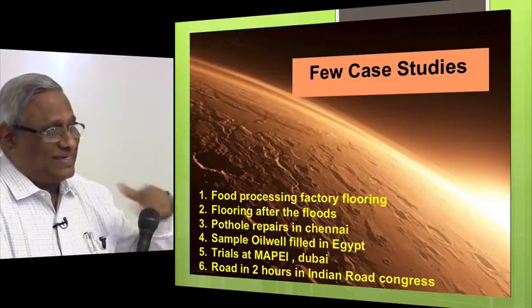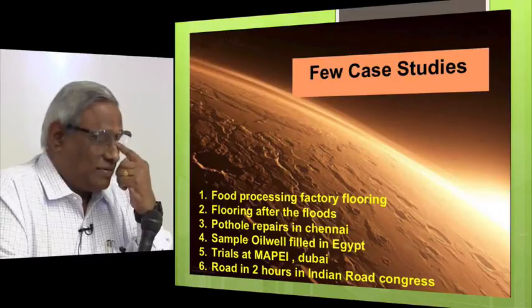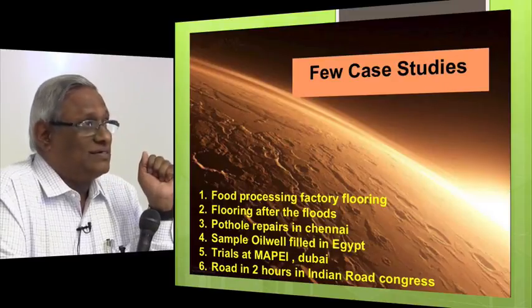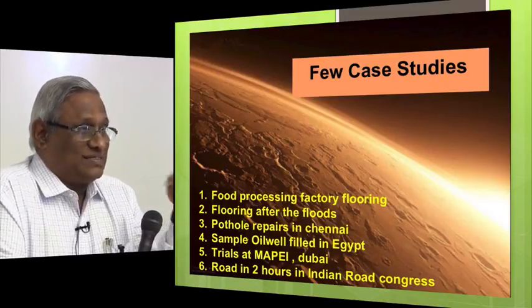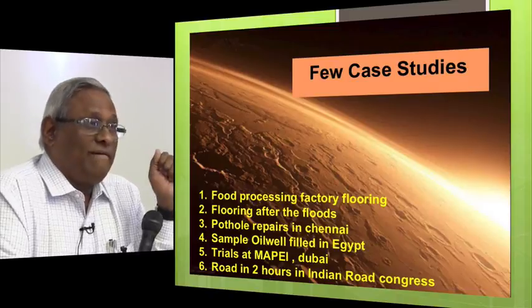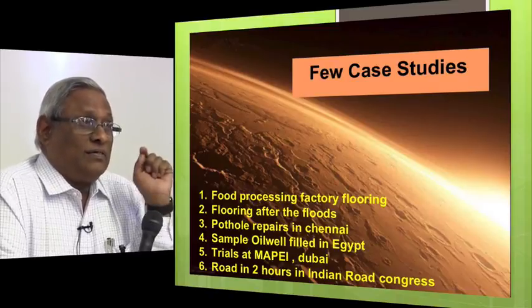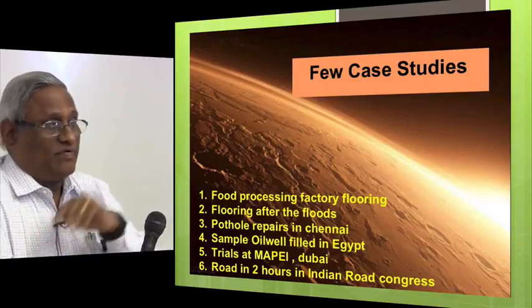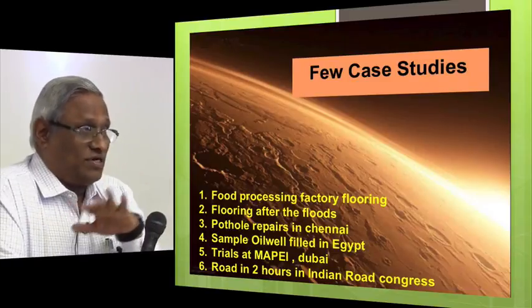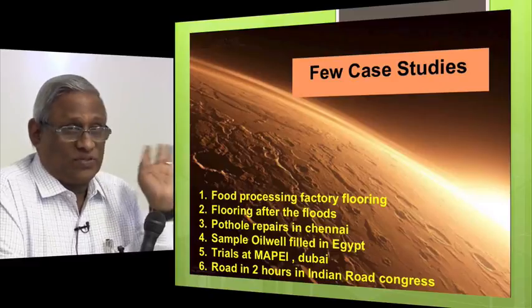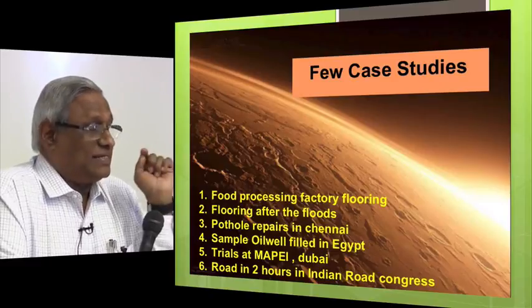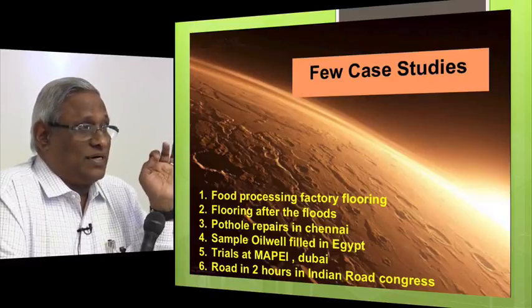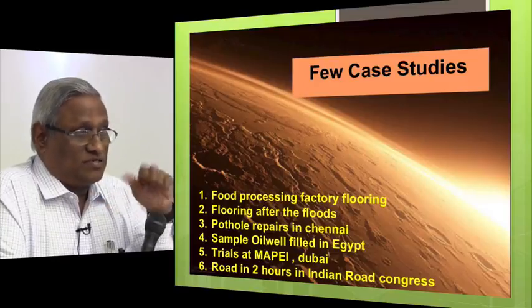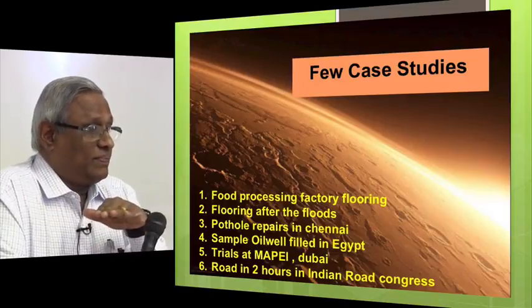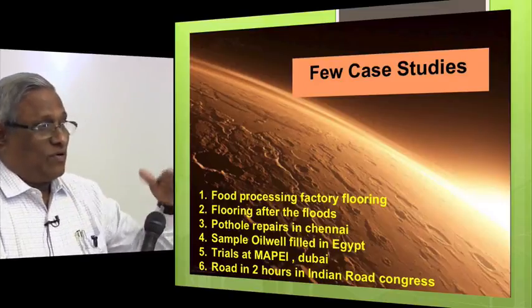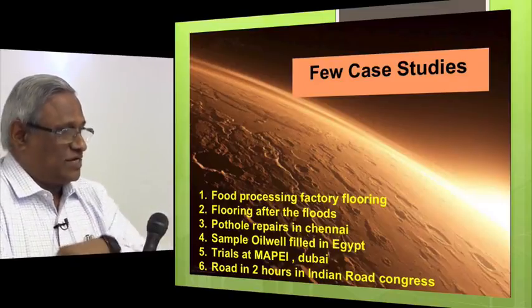And when you mix in your normal cement mixer, that 1 bag mixer, it is very viscous. It's very difficult to take it. So that's one point. Then we started laying the flooring, all absolutely manual, because there's no access to other machinery there and no RMC, nothing. It's about 1,200 square feet, and it was done in about 3 hours. Each batch was one mix, about 350 kilos.